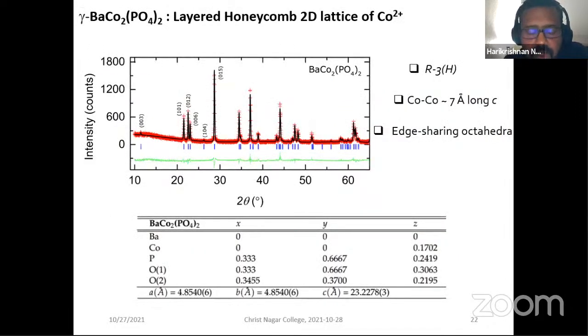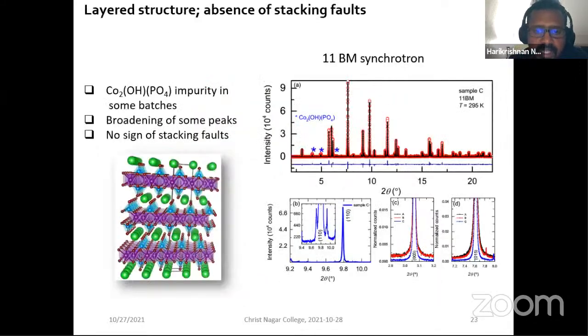Now we study the crystal structure using X-rays. You can look at where the atoms are and find the distances between the atoms. You can ascertain if the cobalt distances are a specific value and make sure that they form a honeycomb lattice. That's the first thing that we do. Once that is decided, you can probe further and see if there are distortions. On the left-hand side, you can see a three-dimensional view of the crystal structure, and what you see in purple are the honeycomb lattices.